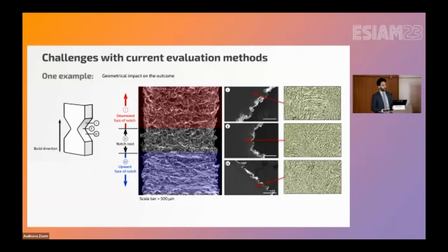If we see the top part of the notch, we can see that the grains have grown quite larger, similar to the effect that we saw for the thickness. But again, why is that? In the case of the notch component, the top side of the notch has a lower cooling rate because the consolidated part underneath is quite limited, and the transfer of heat through the powder is quite less than through a solid material. This will result in a higher temperature on the top side of the notch, resulting in grain growth and ultimately leading to a gradient of microstructure and locally different mechanical properties.